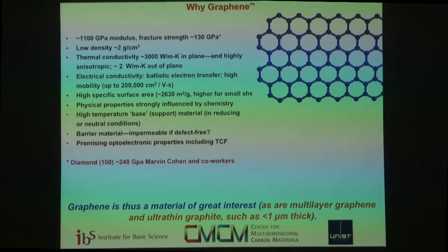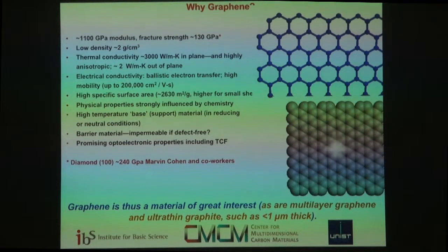There's been a very interesting paper published recently from the University of Manchester from Andre Geim's group. Defect-free graphene has been shown to be impermeable to helium, but it's now known that it's not impermeable to protons going through, and even more so through hexagonal boron nitride. So that was a very interesting result. But it is nonetheless a very interesting barrier material, and I'll show you one example where monolayer graphene can protect a bare metal surface from oxidation, for example. So it might end up being very important for corrosion.